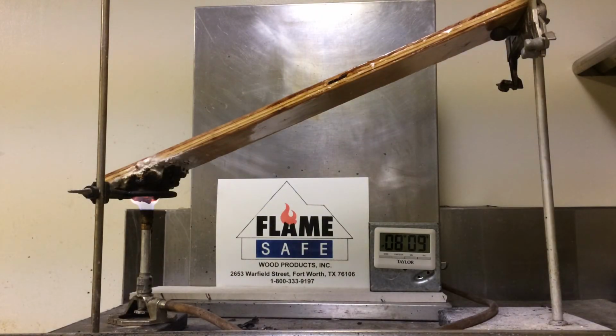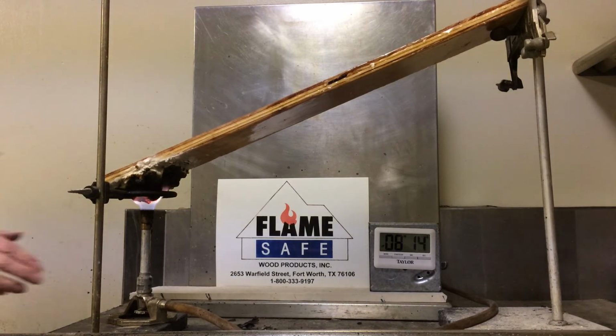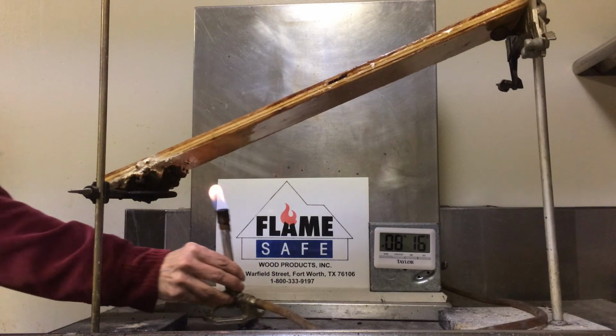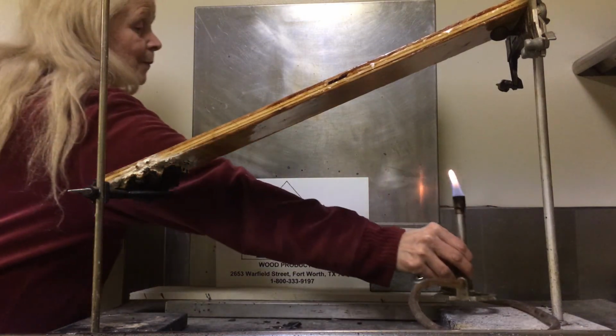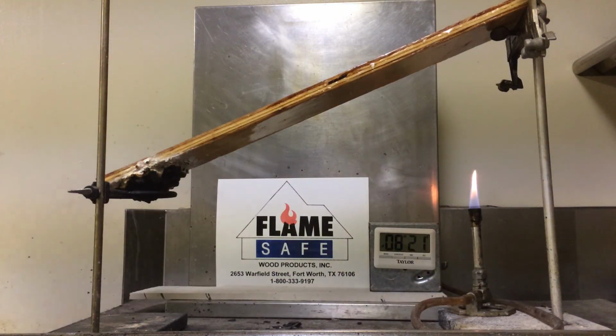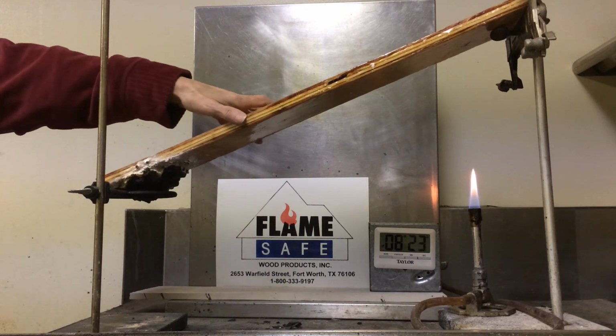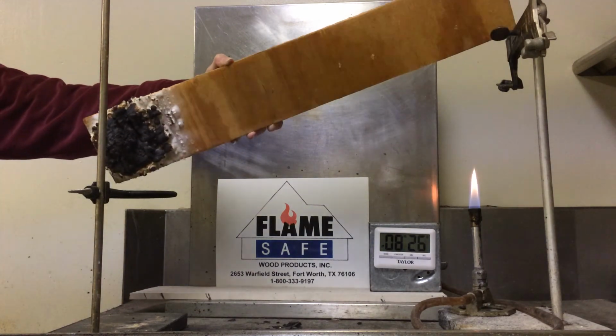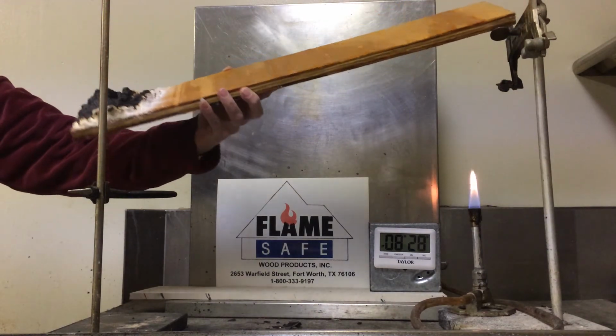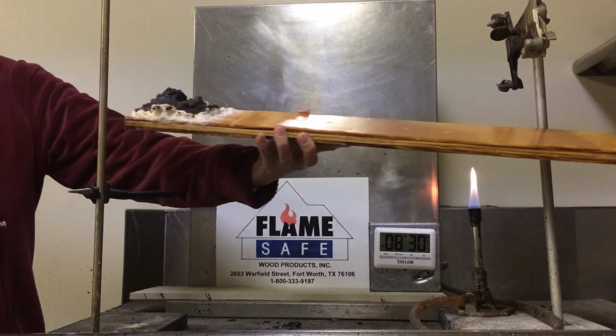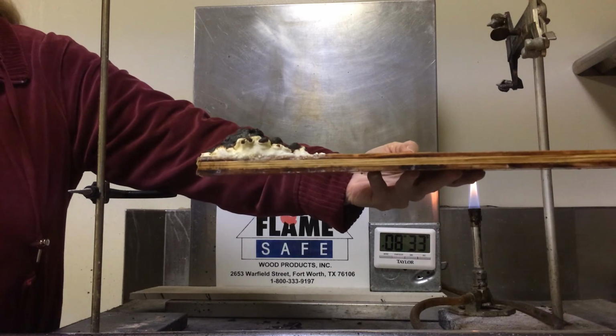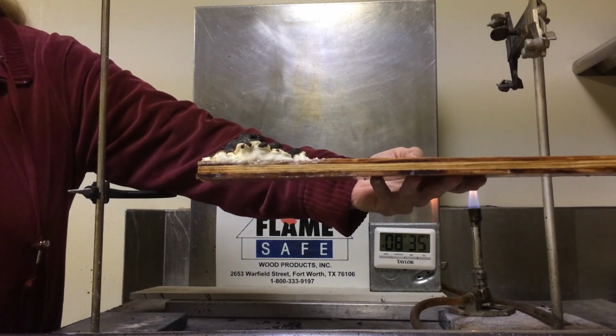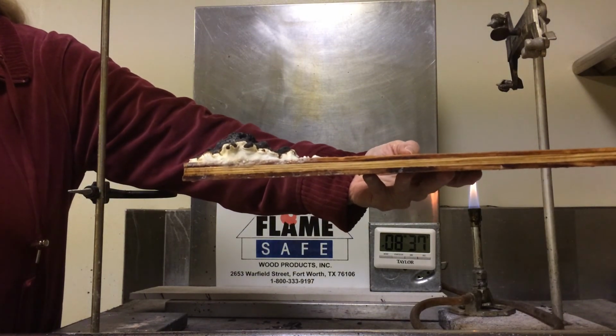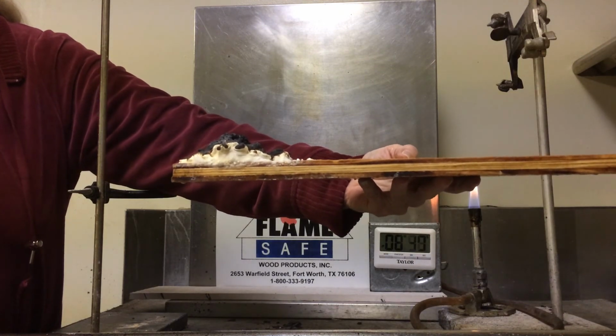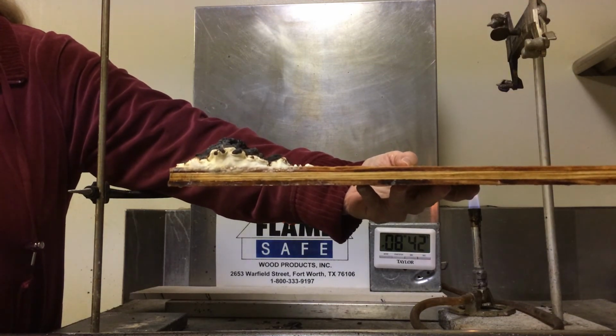At this point, we're going to remove the test specimen from the burner. And please take note and observe the amount of intumescence that has been created. If you will note, the intumescence is approximately 3 times higher than the thickness of the panel.